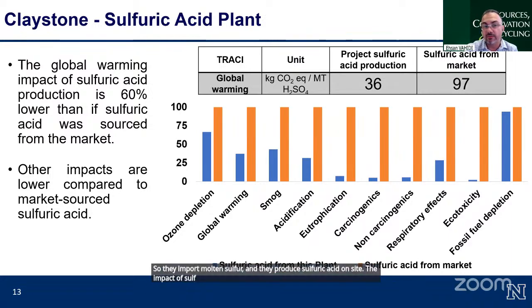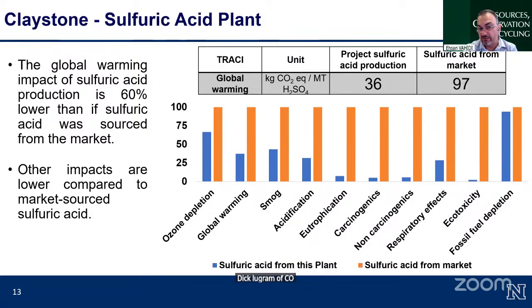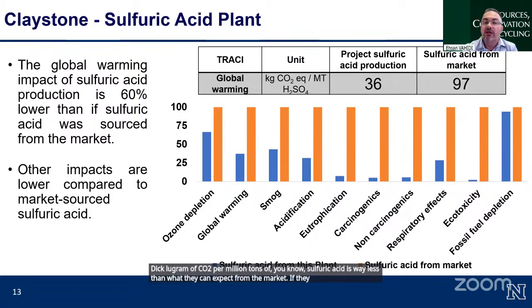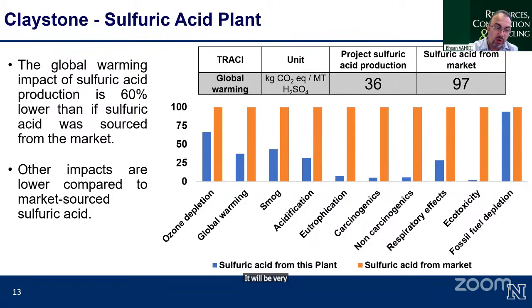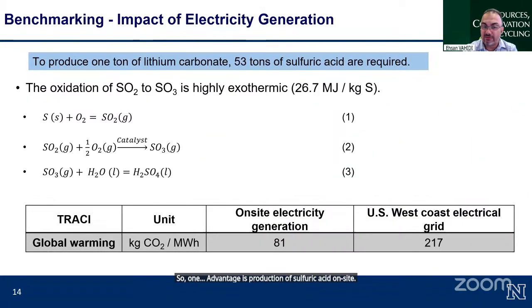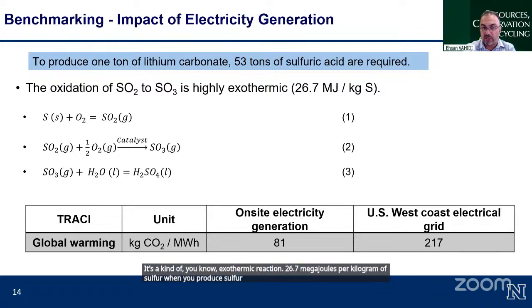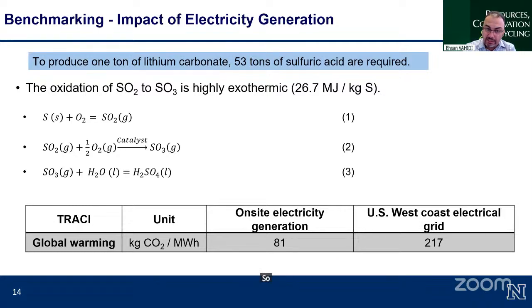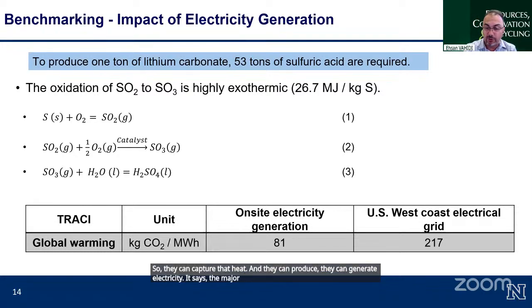The impact of sulfuric acid, the kilogram of CO2 per metric ton of sulfuric acid, is way less than what they can expect from the market. If they buy it from the market, it will be very high impact compared to what they are using in different processes on site. So one advantage is production of sulfuric acid on site. The side advantage of that is when you produce sulfuric acid, it's a kind of exothermic reaction. 26.7 megajoule per kilogram of sulfur when you produce sulfuric acid out of molten sulfur. So they can capture that heat and they can generate electricity. This is the major highlight of the process in Nevada.